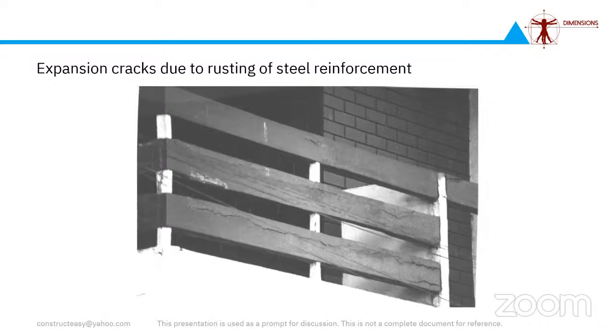One portion of the concrete might be very rich in cement. The other portion might have a leaner mix. It may not have the same cement content. So if the proportion is varying, then in the same concrete member, one region is anodic and the other region is cathodic, and there is a potential difference which is formed, and therefore electrochemistry comes into the picture and the steel starts corroding. So this can be stopped only if the quality of concrete is maintained uniformly.